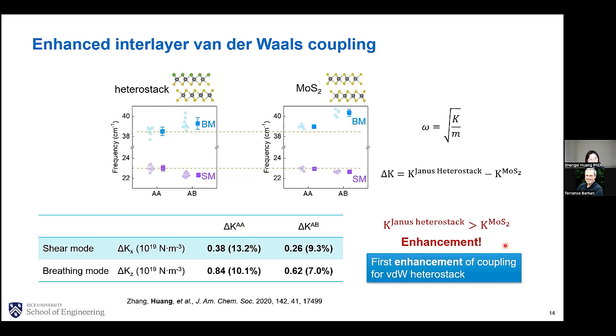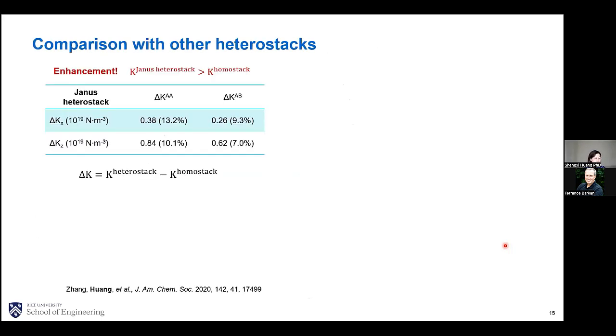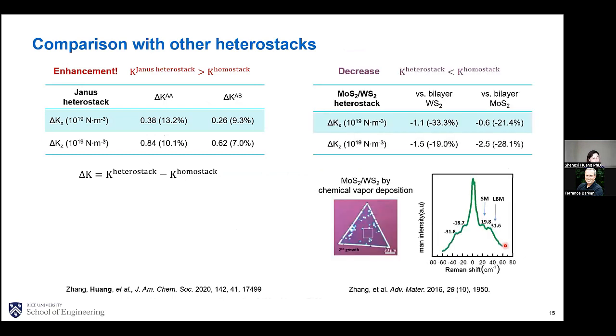If we look at the literature for other van der Waals heterostacks, very rarely do people report the low frequency Raman modes, simply because the interlayer coupling strength is too weak and the low frequency Raman modes are not observable. But we still found a few exceptions. For example, in this work, this is MoS2 and WS2 heterostack directly synthesized by CVD method. And the authors reported the low frequency Raman modes over here.